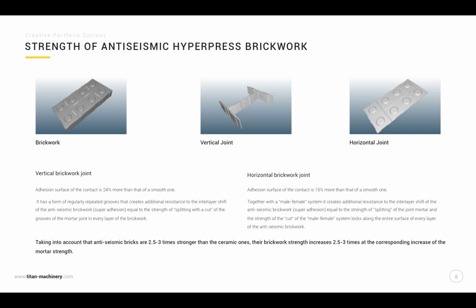Horizontal brickwork joint. Adhesion surface of the contact is 15% more than that of smooth one. Together with a male-female system, it creates additional resistance to the interlayer shift of the anti-seismic brickwork, super adhesion, equal to the strength of splitting of the joint mortar and the strength of the cut of the male-female system blocks along the entire surface of every layer of the anti-seismic brickwork. Taking into account that anti-seismic bricks are up to 3 times stronger than the ceramic ones, their brickwork strength increases 2.5 to 3 times at the corresponding increase of the mortar strength.